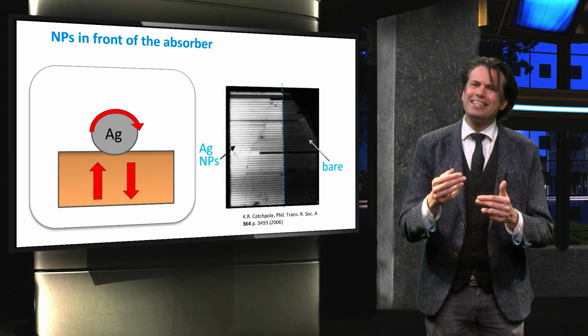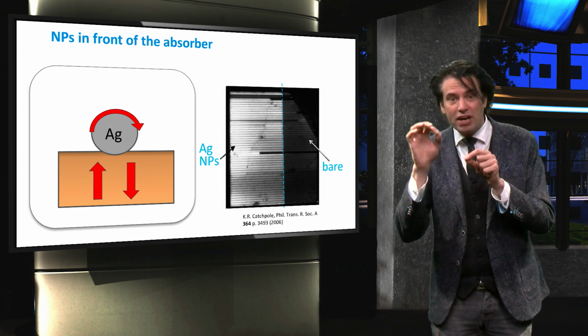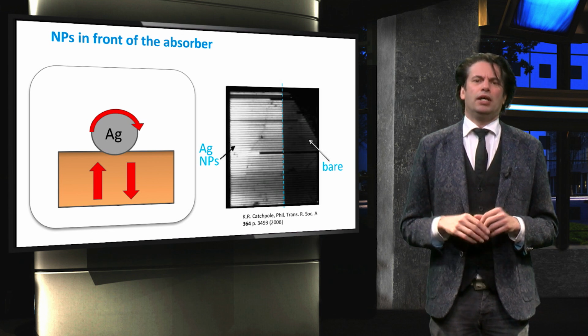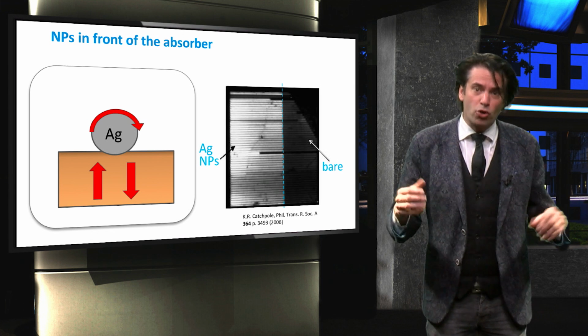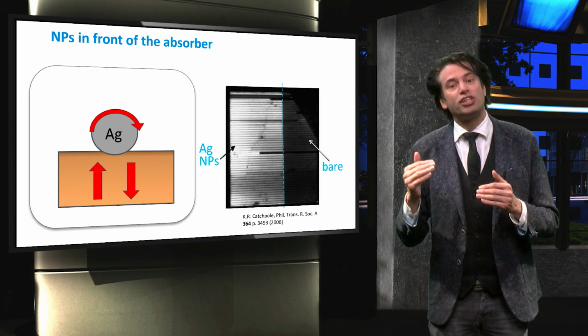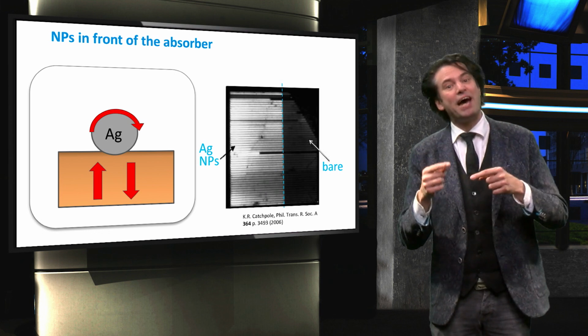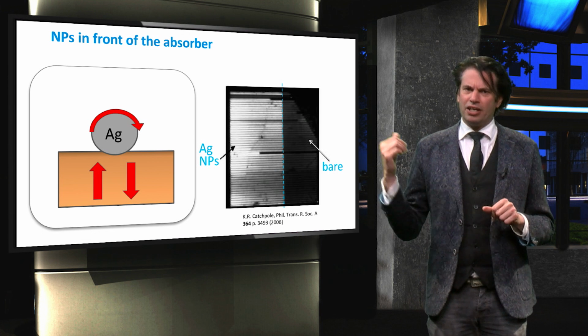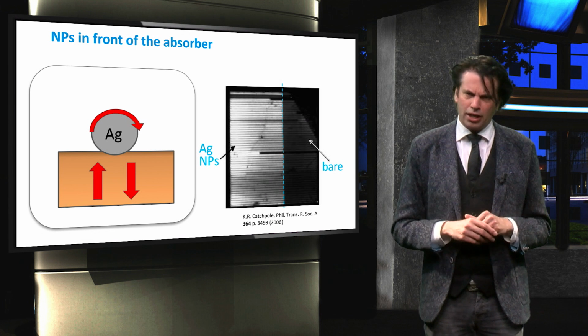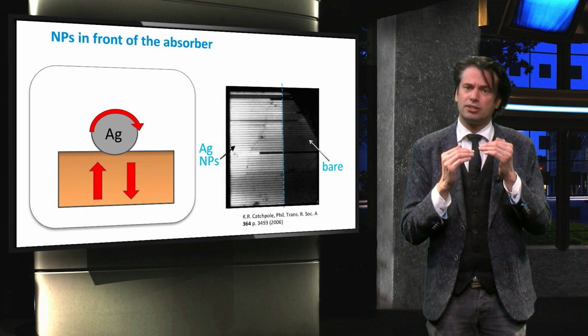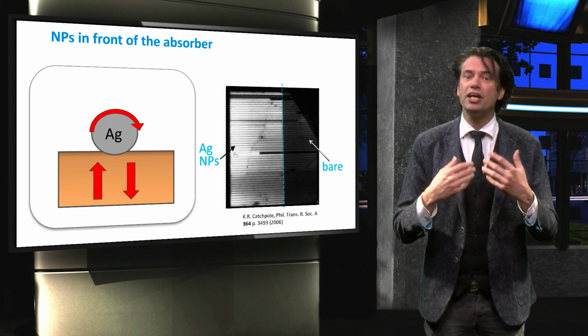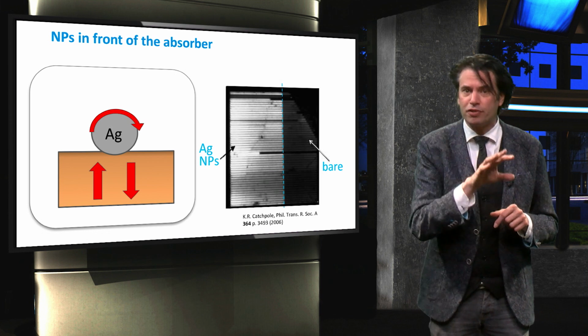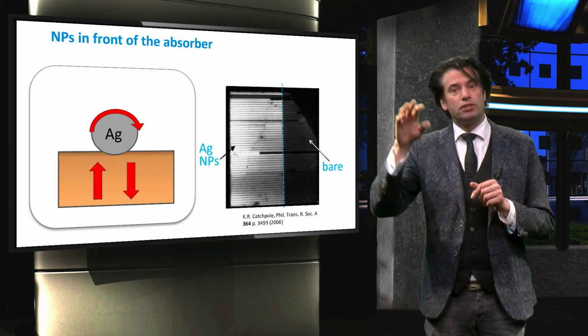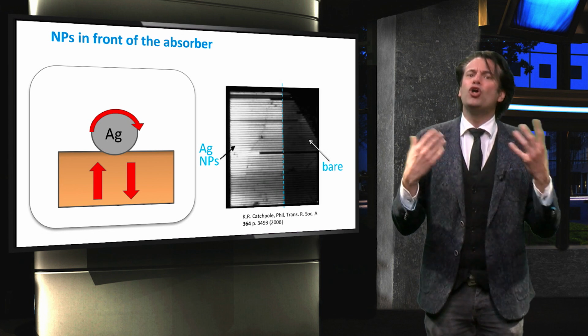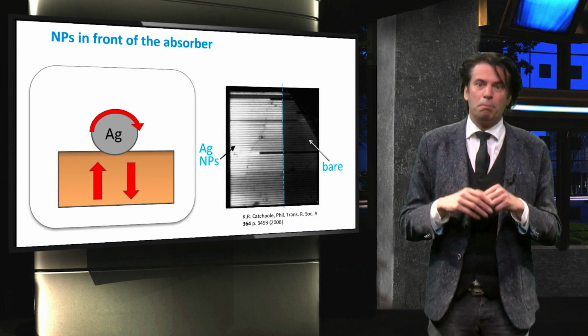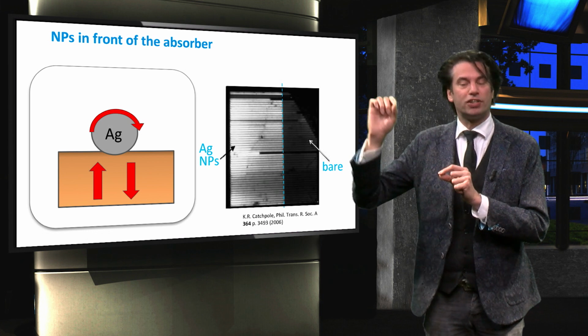The second purpose is light trapping, keeping the light that tries to escape the wafer inside until it's fully absorbed. It's often claimed that nanoparticles on the surface can do this because they preferentially scatter the light towards the side of the high refractive index. So that means back into the crystalline silicon wafer. However, an electroluminescence measurement by Catchpole clearly shows that the photons generated inside a crystalline silicon LED escape more easily from the part of the device that is covered with the silver nanoparticles in reference to the part not covered with the silver nanoparticles. So this proves that there is no trapping effect from the silver nanoparticles, but that the opposite is true. Light is coupled out of the crystalline silicon wafer.